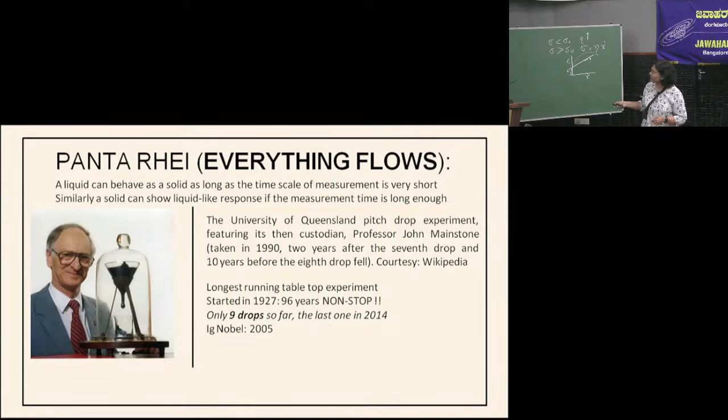It is a crazy experiment, and it got the Ig Nobel Award in 2005. As you know, Ig Nobel Awards are awarded to serious research which first makes you laugh and then makes you think. I think this is a fantastic experiment because it allows you to measure the viscosity of pitch. You know the Poiseuille equation, right? The volumetric flow rate is proportional to the pressure gradient under capillary flow. So from the geometric dimensions of the stem here, they could calculate the viscosity of pitch, and it turned out to be 2.3 times 10 to the power 11 millipascal second.